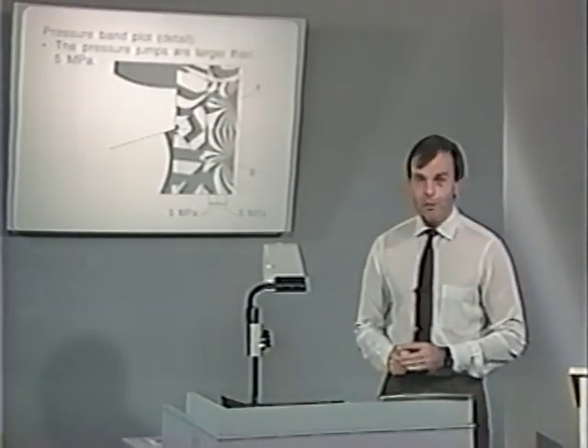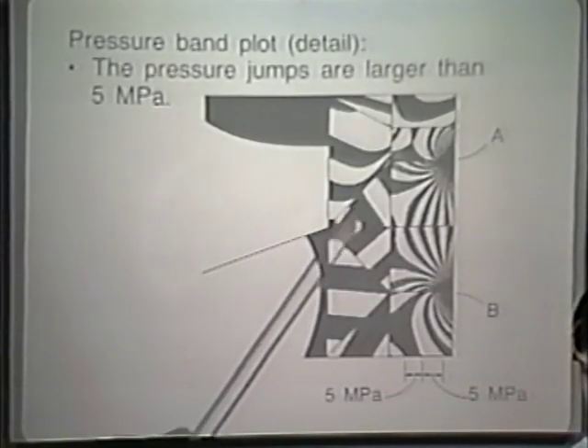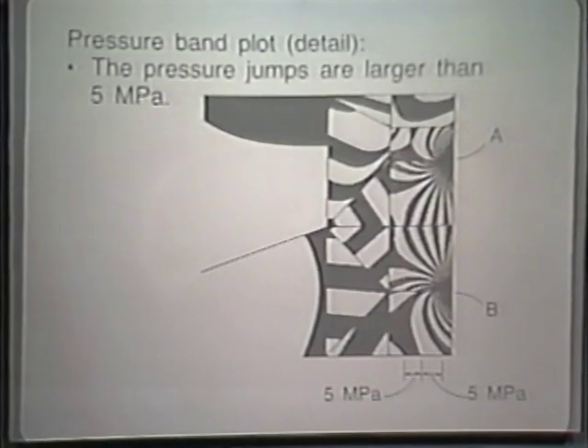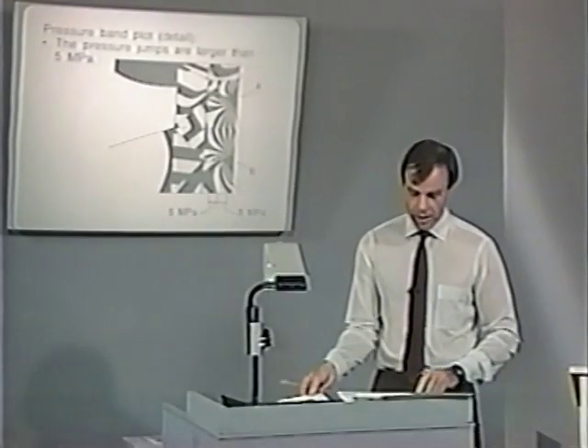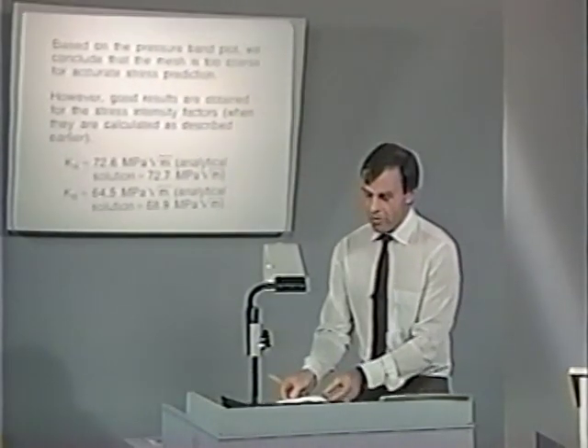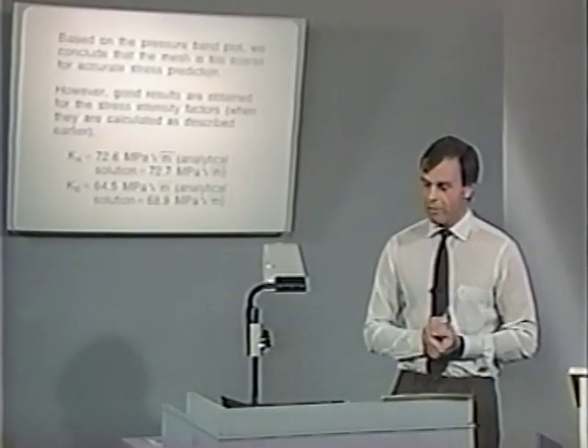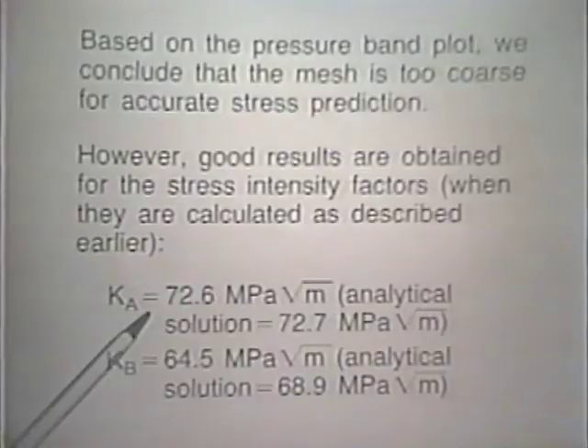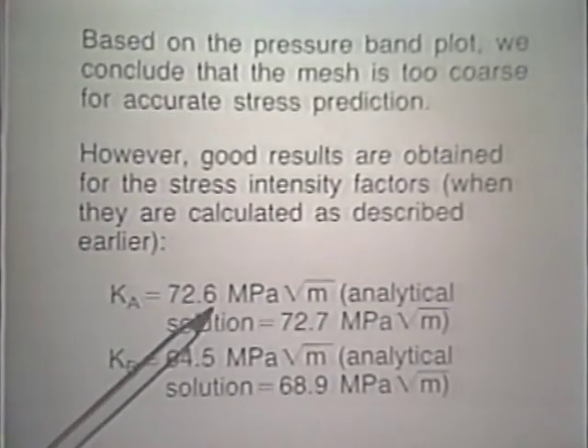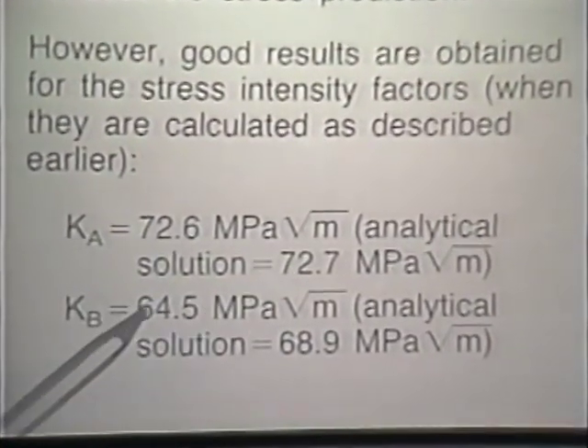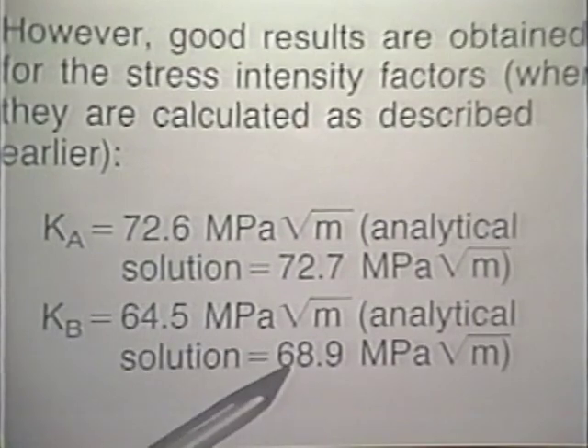If we look at the pressure band plot, I introduced you to those kinds of plots in the earlier example, we find that the pressure jumps are really larger than 5 MPa. For example, you can see it right here, right there, and right there. So it's a coarse mesh, and certainly the stresses are not very well represented with this mesh. However, if we look at the stress intensity factors that we wanted to estimate in this analysis, because they will tell us whether the crack will propagate or not, we find that for Ka, we get an excellent solution. For Kb, the solution is not as good, but perhaps still acceptable.